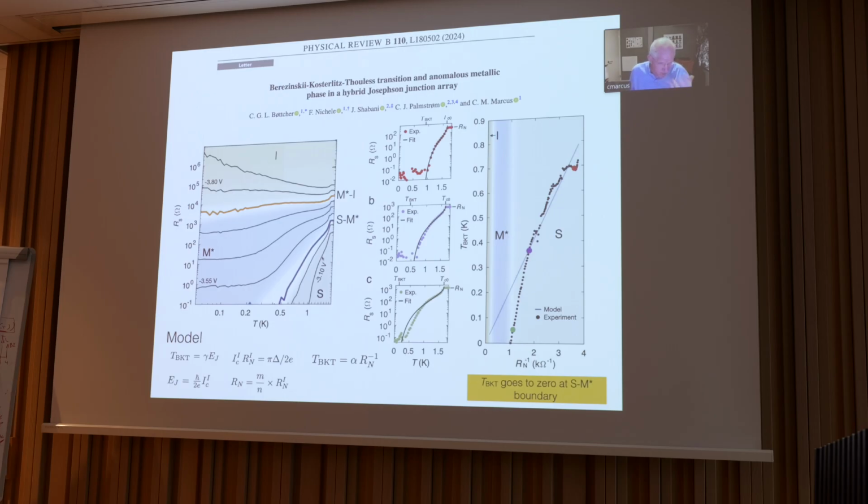And the speculations are based on experimental data, and they say that, for instance, in this superconducting regime, let's just start with the regime where it's well-behaved in superconducting. In the superconducting regime, the system is very well described by a Kosterlitz-Thouless transition. As the temperature rises, this resistance goes up until the system becomes normal, and even the superconducting islands become normal. But over several orders of magnitude, it's a good fit to Kosterlitz-Thouless temperature dependence. And the Kosterlitz-Thouless temperature is a parameter that is extracted from that fit.